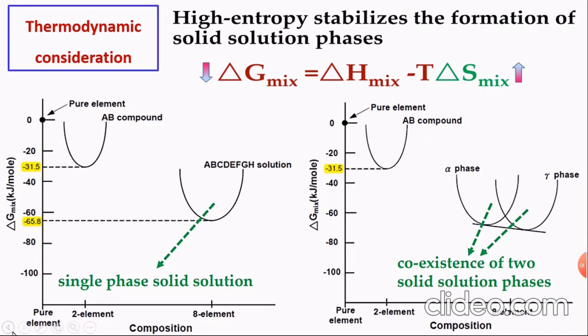And according to the Gibbs free energy plot with composition, we can have single phase solid solution. If we have delta G of mixing, or Gibbs free energy, minus 65.8. For example, with decreased Gibbs free energy, we can have compounds. If we reach this level, we can have coexistence of two solid solution phases. So the value of Gibbs free energy is very important in determining the type of solid solution of your system.